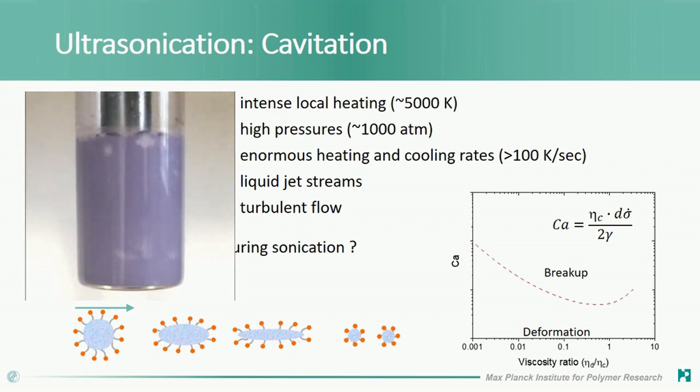The bubbles that we are forming with a sonotrode working at 20 kilohertz will be about 150 micron in size. I mention the frequency because the higher the frequency, the smaller the bubble will be. But you will also be making more bubbles. But because the bubble is smaller, when the cavitation happens, it contains less energy.